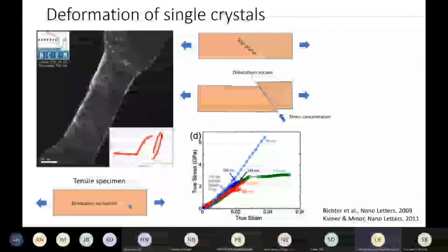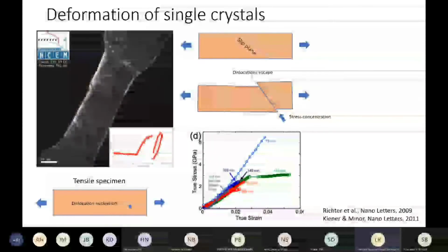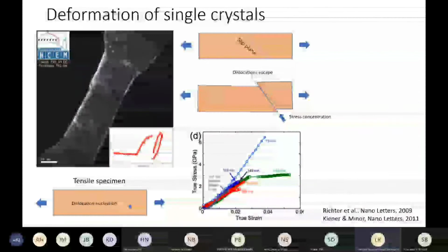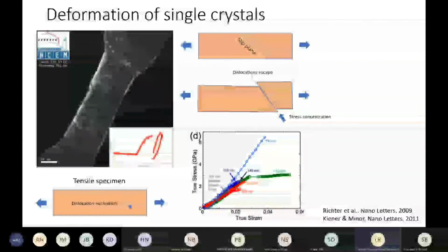As a result, these samples, although they have very high strengths, see, look at the kind of strengths you can obtain in copper single crystal. Your actual strength of copper in the bulk form is about 600 MPa or even lesser. But when you go to a very, very low size scale, you see that the true stress is almost 6 GPa. This is about 10 times higher. So you can actually strengthen the material quite a bit, but the ductility is very, very poor.